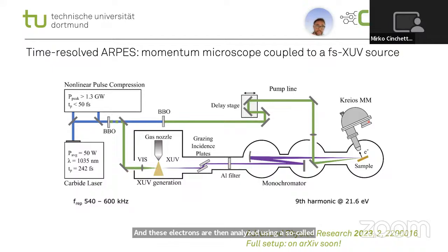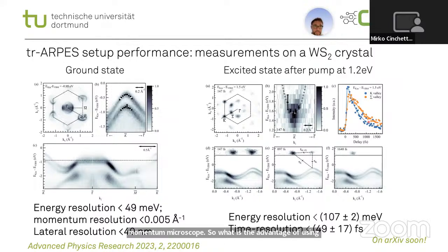So what is the advantage of using such a momentum microscope? Here you see what we can measure with this instrument. We performed some characterization measurements on another 2D material, which is tungsten disulfide. And here you see first what we can do in a static experiment, so without the pump beam. What we measure in the photoemission experiments is basically the photoemission intensity, which is given here in this gray color scale, as a function of the momentum of the electrons in the plane parallel to the sample surface. So we have here the whole photoemission intensity in the whole Brillouin zone. Here you see these circles that correspond to the K valleys of tungsten disulfide, which are actually quite famous in the context of valleytronics. So we can really image these points in one shot.